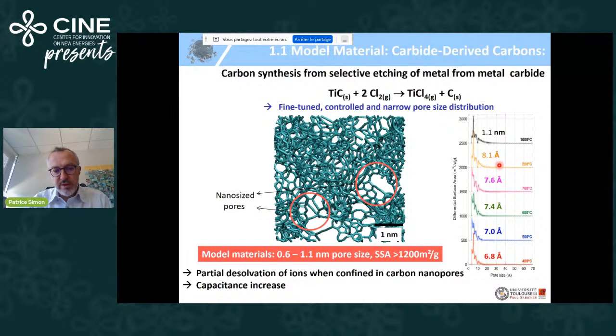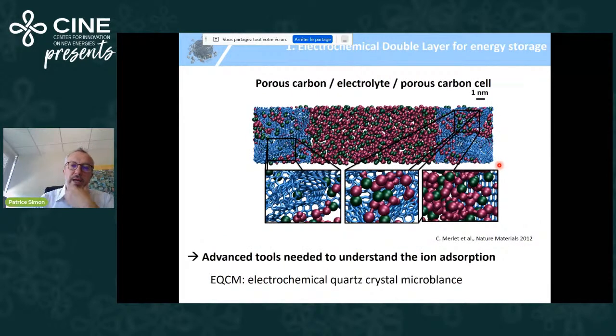And what we have shown with these materials is that when you use carbon pores with a size less than the, I would say, solvated ion size, you force the ion to partially desolvate to enter these pores. And then when you confine ions in these pores, you have a big capacitance increase. So to try to go a little bit further, you need advanced tools to understand the ion adsorption in these confined small pore size materials.